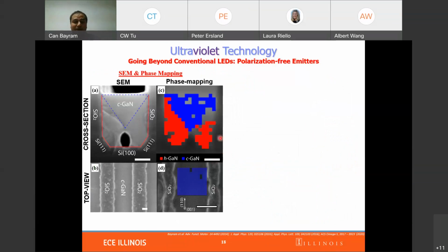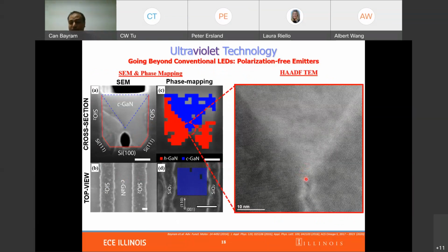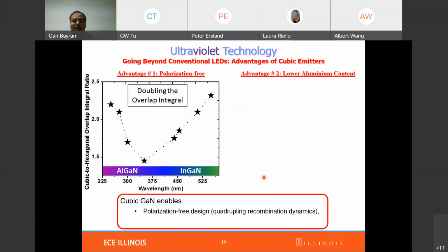And here is the phase mapping that has an accuracy of 20 nanometers. So we have mapped these groove structures and show that the incoming phase is Wurtzite and the resultant phase is zinc blende. And here's a top SEM surface showing 100% cubic surfaces. And this is the atomic resolution image showing the stacking formation that enables the phase transition. Now, this material is important because by adding more aluminum or more indium to go to the UV or visible spectrum, you are non-polar, so you can increase your recombination dynamics significantly.